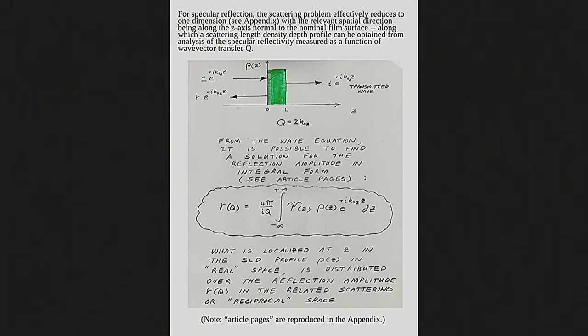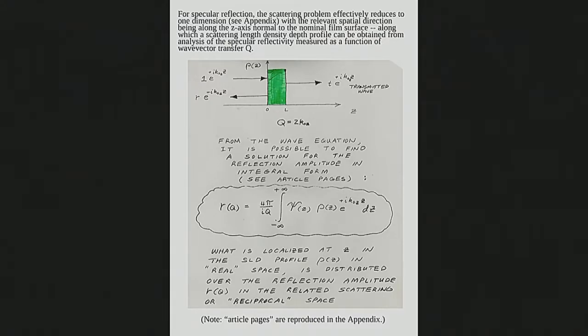For the specular condition, all of the momentum transfer is normal to the plane of the film, so all information is a function of depth. Any information in the XY plane — because there is nothing to scatter neutrons from the homogeneous potential along in-plane — means we have basically a one-dimensional problem. We can disregard the X and Y in-plane components, unless there are really big differences in the density distribution in-plane. Then we have to look at non-specular scattering, where the momentum transfer is tilted off the normal — but that's a different experiment.